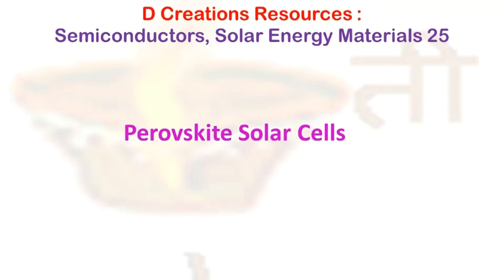Now in the 2-step process, the metal halide, for example PbI2, and organic compounds, for example CH3NH3I, are spin coated in separate subsequent films, and alternatively metal halide films can be coated and annealed in a chamber filled with organic component vapors, which is called vacuum assisted solution process, VASP.